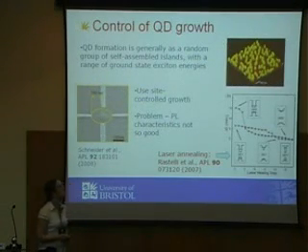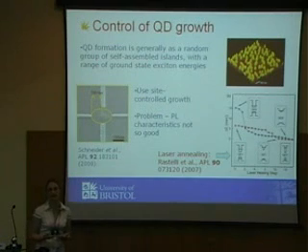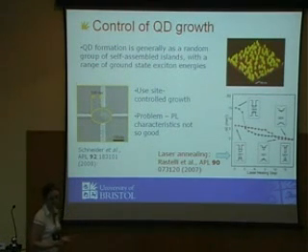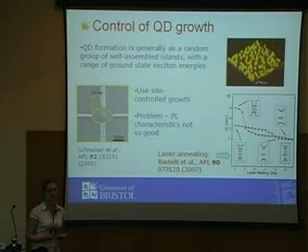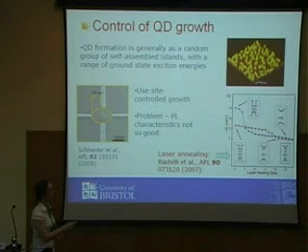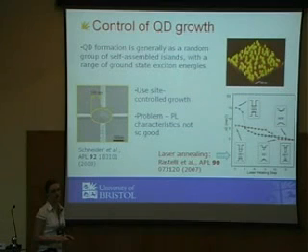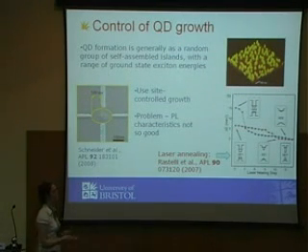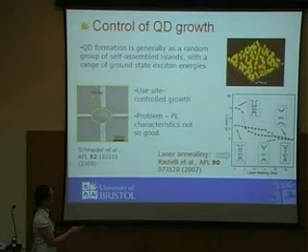So quantum dots, the ones that we look at, are self-assembled quantum dots. And self-assembly is a crystal growth technique which produces very high-quality quantum dots. I'm showing you an AFM image of these quantum dots. What we do is deposit indium arsenide slowly onto gallium arsenide. And that allows the formation of these so-called nano islands here.